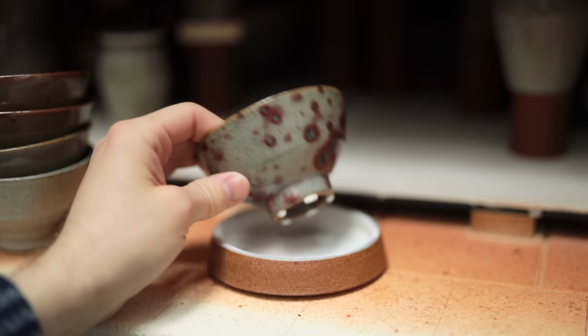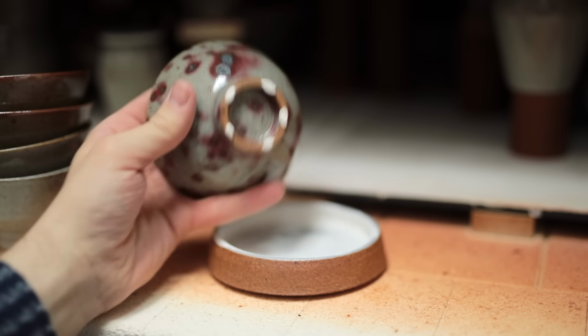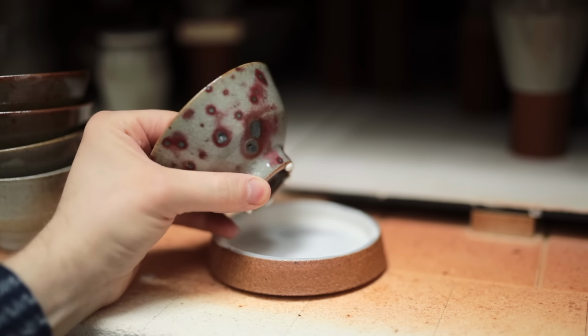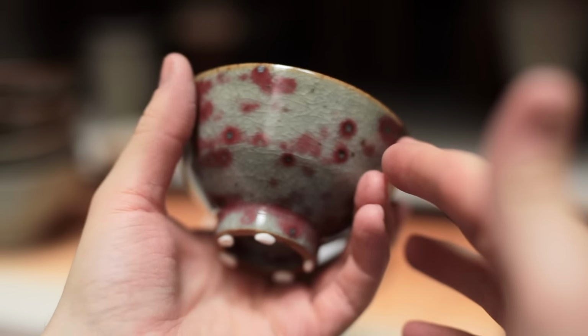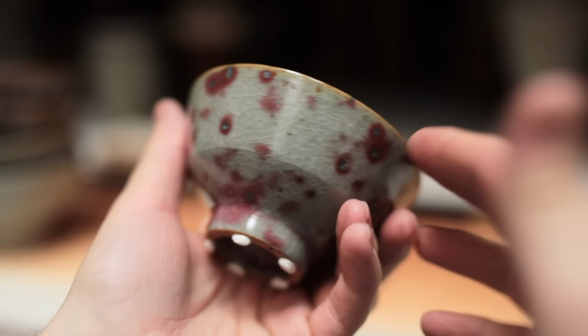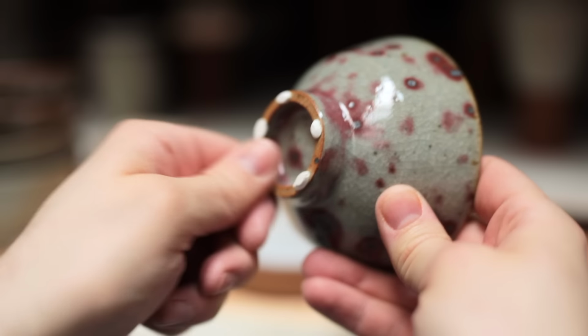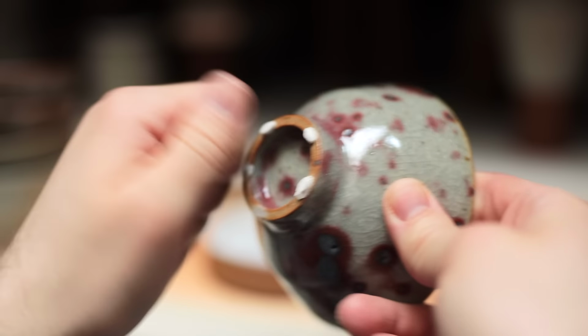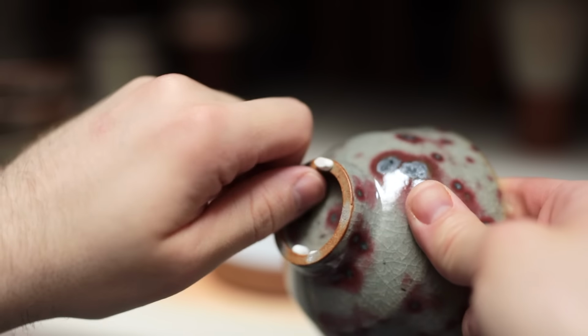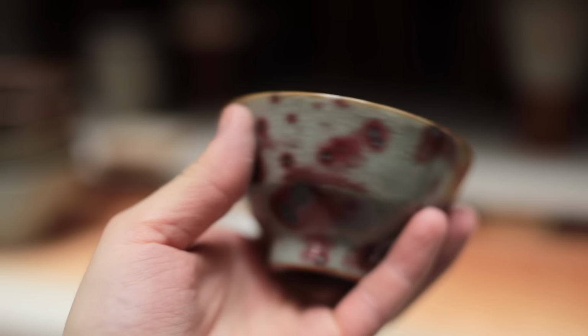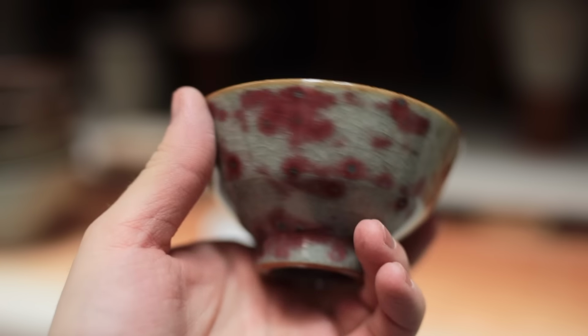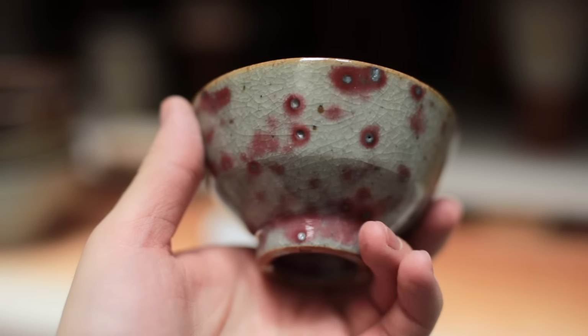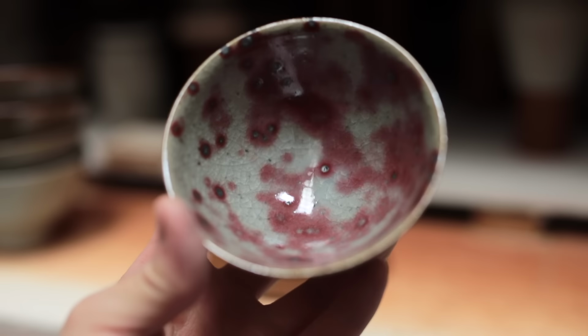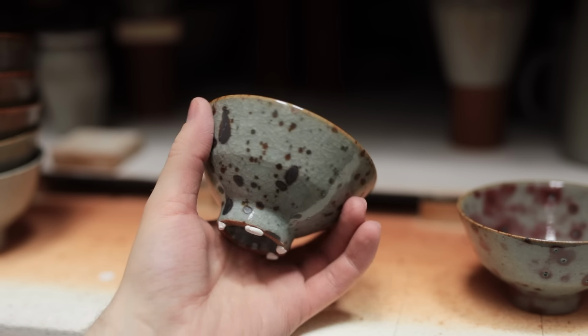And well, it is different. The glaze is now fired to the correct temperature. It's more glossy, and more of the bronze has broken through the glaze to form these metal spots, which does make it look a tiny bit like it's been riddled with bullets. Yet I do still, surprisingly, really like it, meaning the second firing really did make all the difference, which is infuriating in a way, as I can't make pots that all require being fired twice. But maybe all they need is firing to the correct temperature and for the bits of bronze to be closer to the surface.